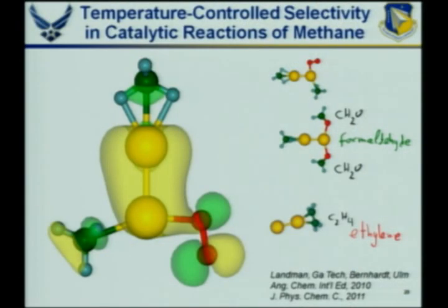And what's happening is, at low temperatures, oxygen here can bind to this gold dimer. Electrons get donated from this gold dimer into antibonding orbitals in the oxygen, and it weakens this bond. So the oxygen bond gets broken, the oxygen can then migrate, and they react with each of those methyl radicals to form formaldehyde. Turns out if you put different metals in here, you can get different products. You can get alcohols also formed.